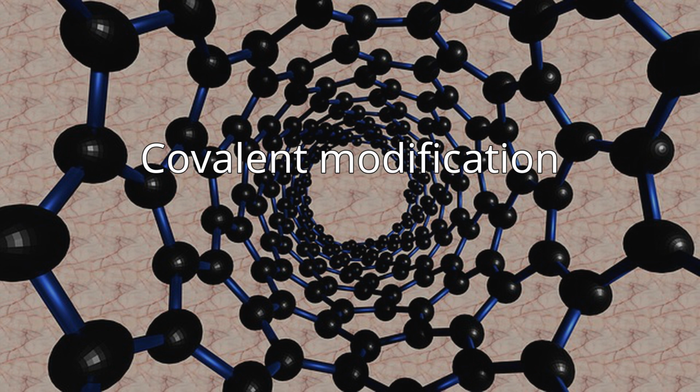The functional groups can be attached onto the side wall or ends of the carbon nanotube. The end caps of the carbon nanotubes have the highest reactivity due to their higher pyramidization angle, and the walls of the carbon nanotubes have lower pyramidization angles, which means lower reactivity. Although covalent modifications are very stable, the bonding process disrupts the sp2 hybridization of the carbon atoms because an sp3 bond is formed. The disruption of the extended sp2 hybridization typically decreases the conductance of the carbon nanotubes.